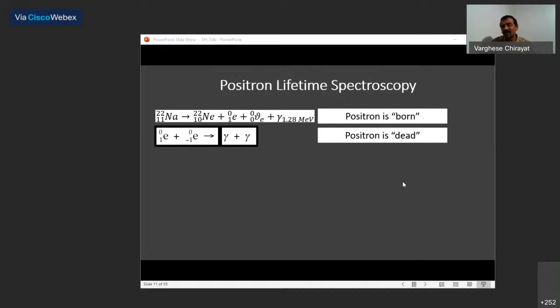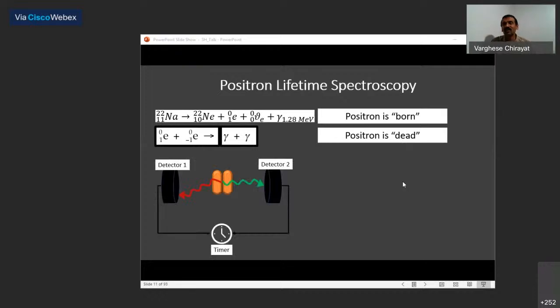What you have measured on your timer is the amount of time the positron has spent inside the material before it annihilated. This is what we actually do in positron lifetime spectroscopy. You do not use your eyes; you have detectors which are sensitive to gamma rays. As shown here, you have a set of detectors with a positron in between them, and then you have 2 gamma rays coming out. Mind you, these are not the two 511 keV gamma rays. One of them, let's say the red one, is the 1.28 MeV start gamma ray. When it reaches detector 1, it tells detector 1 that the positron is born. When the 511 keV gamma ray reaches detector 2, it tells detector 2 that the positron is dead.